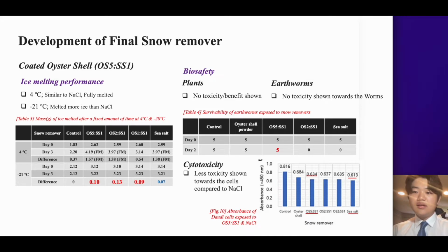From Figure 10, in the case of cell testing, less toxicity was confirmed with all ratios compared to salt, but there was no significant difference in terms of toxicity between different ratios. For other ratios, all aspects other than the safety of earthworms showed equivalent results, but in the biosafety test with earthworms, safety was confirmed only with OS5-SS1. Therefore, it was determined that OS5-SS1 was the best deicer.